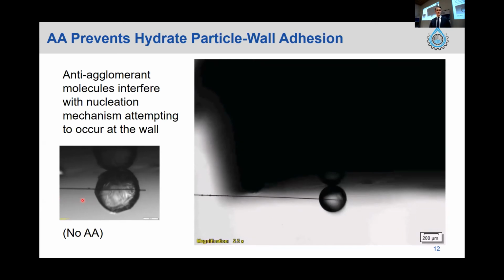So just for comparison, we have here the last picture of that 1 hour annealing period. So you can see that film that had formed. And basically here is a video of a 1 hour time lapse for a hydrate particle forming with 0.05 weight% anti-agglomerant in the system. So I'll show you how that played out now.